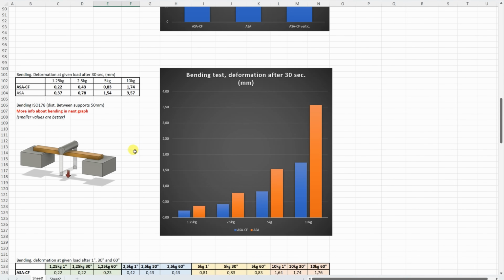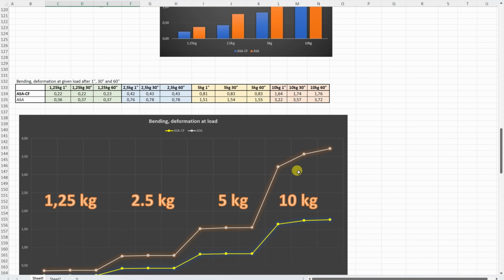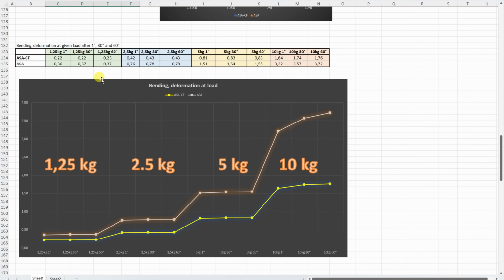On the 3-point bending test, here we can see the deformation under these loads after 30 seconds. Smaller values are better, so definitely the carbon fiber ASA is stronger, stiffer in this test. But this is more interesting because here we can see these deformations after 1, 30 and 60 seconds. And not only is the carbon fiber ASA stronger, with smaller deformation, but also under the 10 kilogram load, look at this. This is more horizontal, so less deformation during the time compared to the regular ASA.